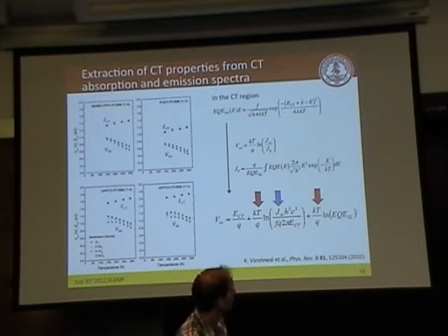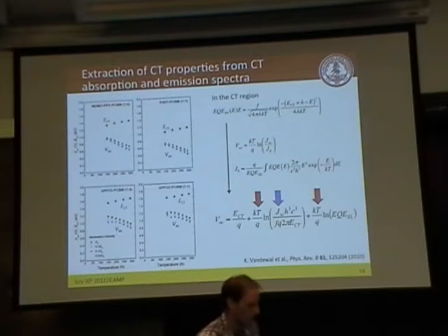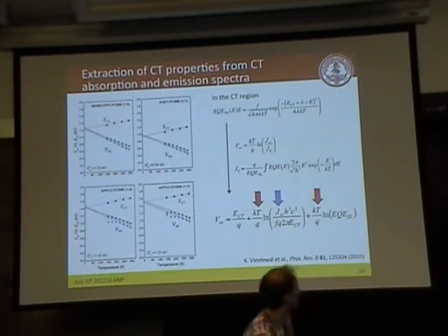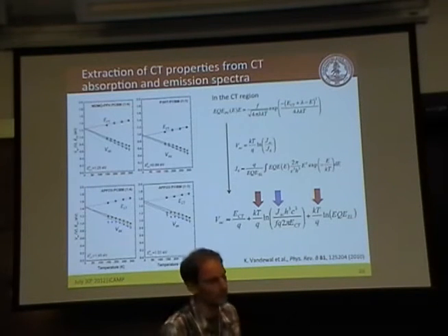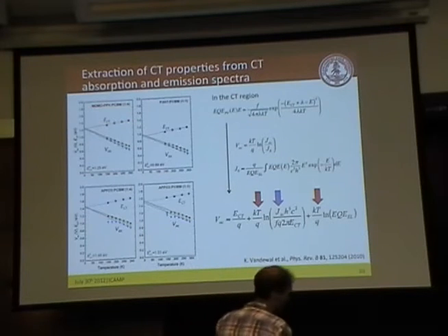This is VOC measured at different light intensities, and you see that VOC indeed rises if you lower the temperature. What should also happen is that if the temperature is 0, they should merge together. And this is what you see. They go together.